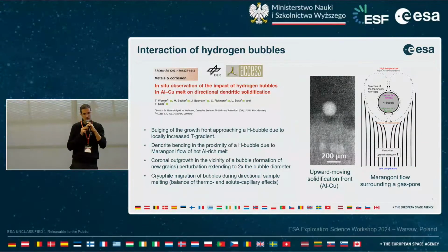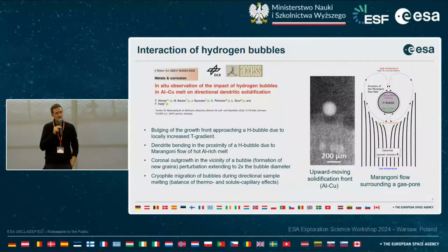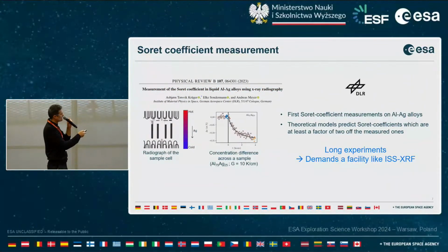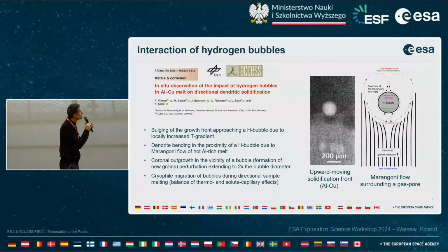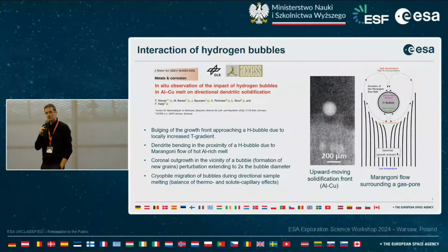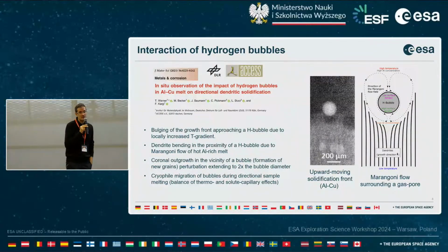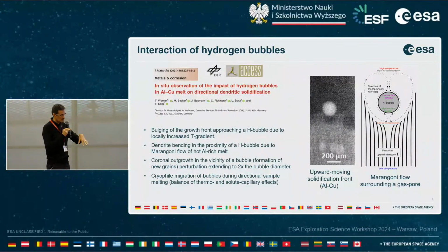Another highlight that I would like to present is a work again by DLR and in collaboration with Access. It was carried out in the framework of the PhD of Thomas Werner. This work was part of the work of Elke Sonderman. So it was a study on the interaction of hydrogen bubbles during the solidification of aluminum alloys as well. It is well known that in aluminum alloys you have hydrogen, dihydrogen, that is inside the liquid and the solid.